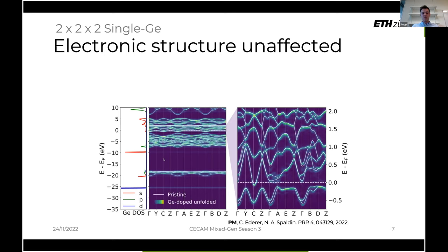And so in here, in particular, what you see in the white line is the pristine band structure, which is a detail of the one on the left. And in the colored line, we see the unfolded supercell band structure. And then on the very left, we see the germanium density of states. The first thing to note is that there is very little or no germanium states near the Fermi level. So the Fermi level resides around here.